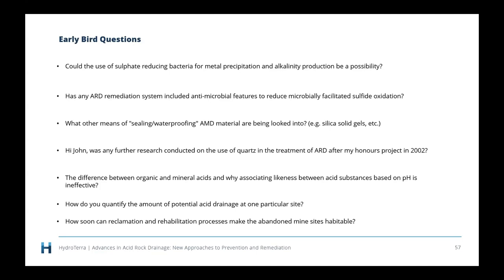So there are sulfate-reducing bioreactors that are used at a variety of sites now, and also some sites where they've made wetlands that have sulfate-reducing bacteria within them. And they do remove the acid and iron and basically remediate the ARD. The only drawback with them, and I think it's a significant one, is that what they do is they precipitate pyrite. So what you end up with is a whole lot of organic material through which is scattered fine-grained pyrite. And if you let that come in contact with oxygen, you'll get all that acidity removed back again really quickly. So disposal of the material within the sulfate-reducing bioreactors or the wetlands is a key to make sure that it can't possibly oxidise.